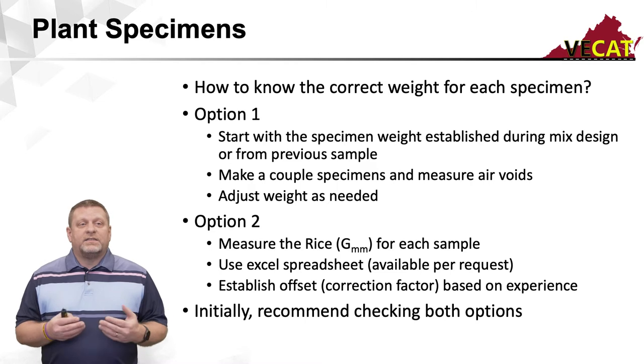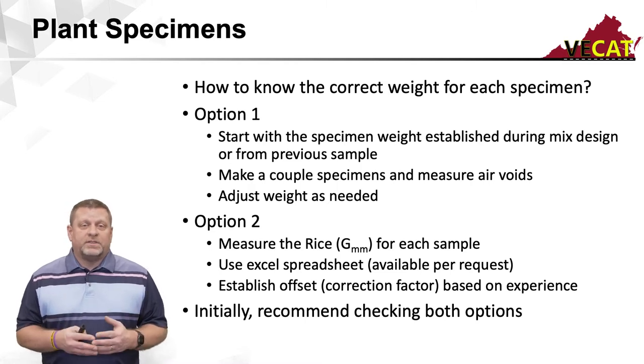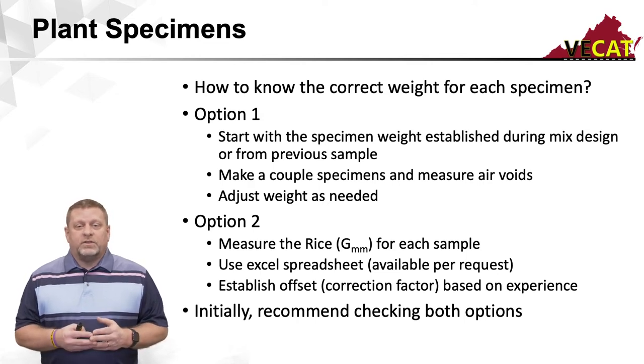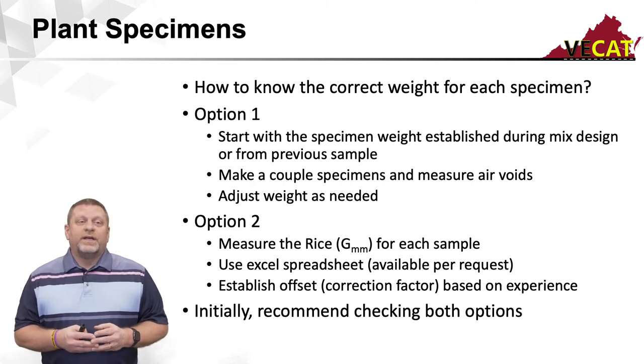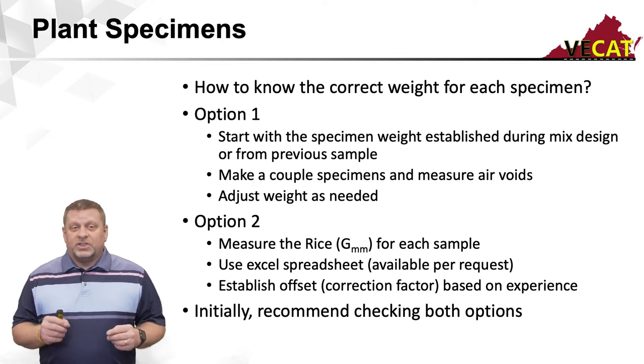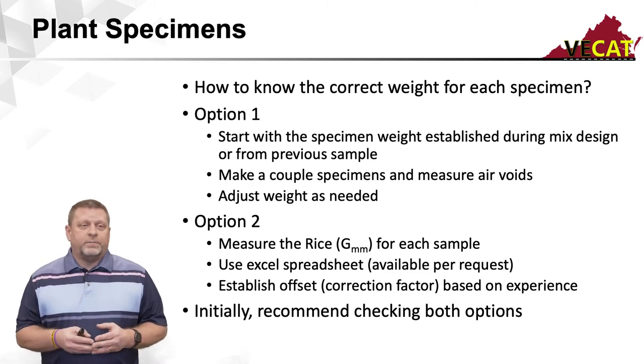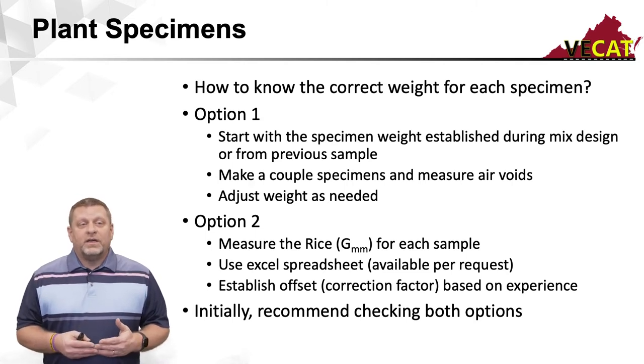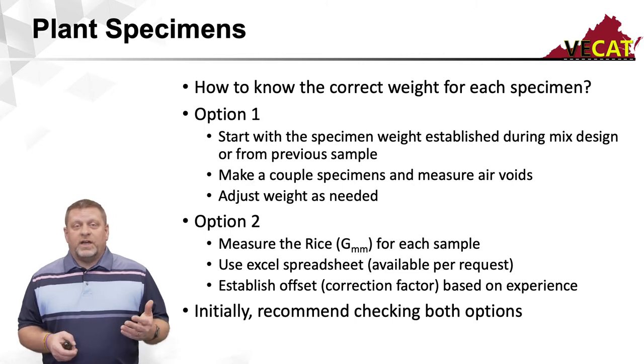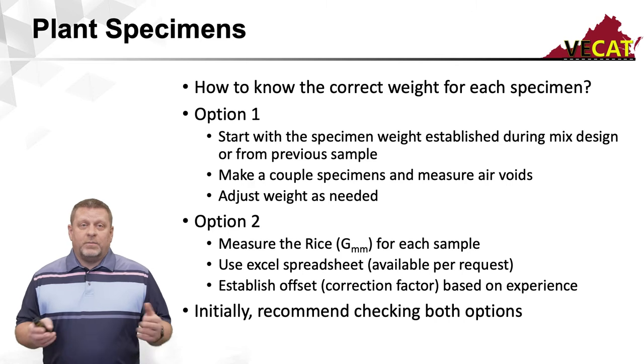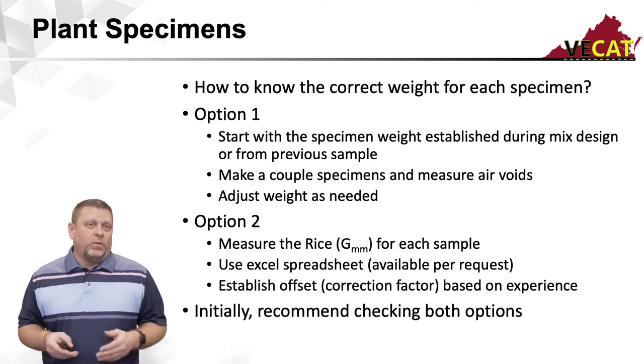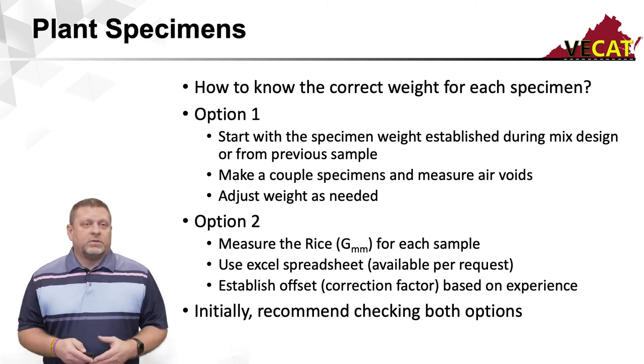This Excel spreadsheet was designed by NCAT — you can contact me or reach out to your local DOT district lab and they should be able to supply it to you. There is an offset or correction factor you may have to adjust in the spreadsheet depending on your specific mix. I recommend initially doing both options — start with the weight from your mix design, run your rice, and compare the two weights to see how close they are. You may even average the two weights. It becomes a little bit of personal experience.